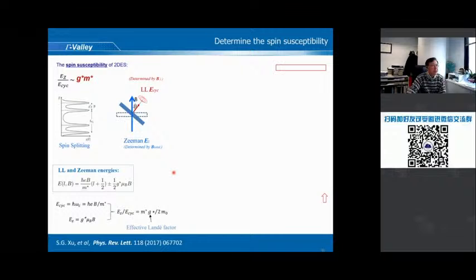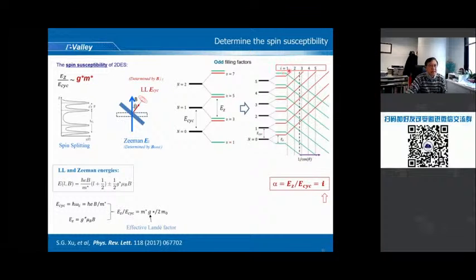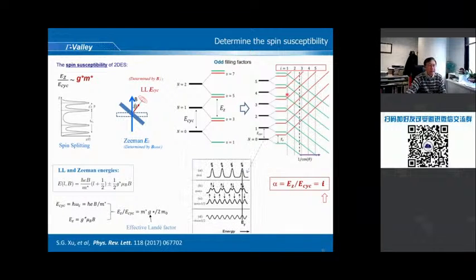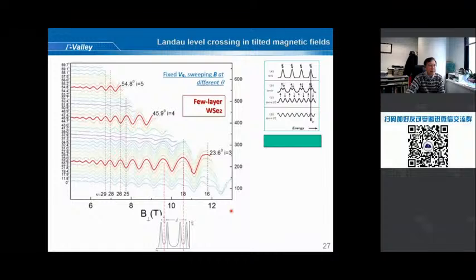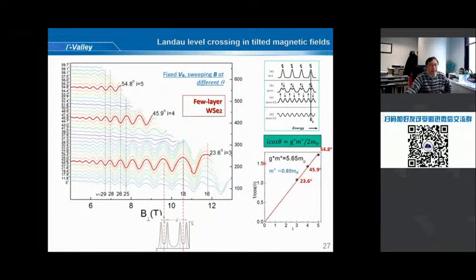So it's the beginning. Then here is the data that we performed on this sample. Now, the aim is to identify the ratio, or I list here the first crossing point, second crossing point, and third crossing point. In principle, we should see the Landau level patterns shift, split, and inverse intensity, and so on. And that's the experiment data. So we measured it. And we do identify these crossing points at 23.6, 45.9, 54.8, and so on. So we identify 3. But the problem is, how do you know this I is 3, 4, 5? It's not 1, 2, 3. The principle is this.